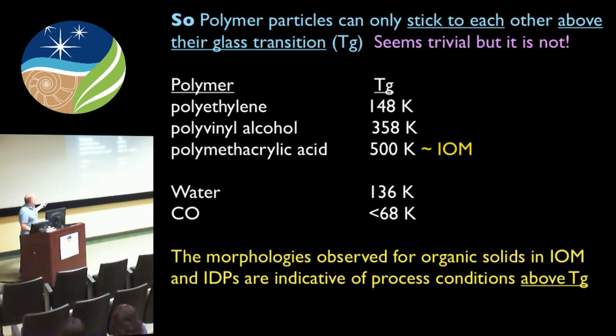So for very simple polymer systems, if you can frustrate polyethylene from crystallizing, it will eventually reach a glass transition at 148 K. But you put some functional groups on it, like alcohols, and all of a sudden the glass transition goes way up. You put some carboxylic acid groups, polymethacrylic acid, and now we're talking 500 K for a glass transition.